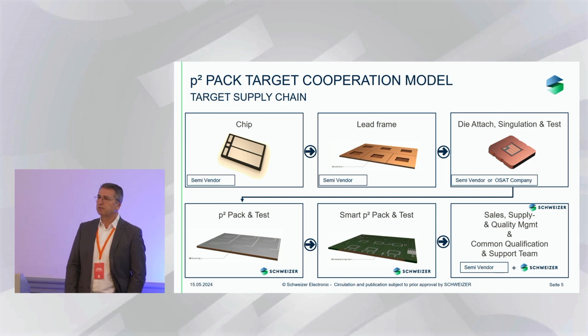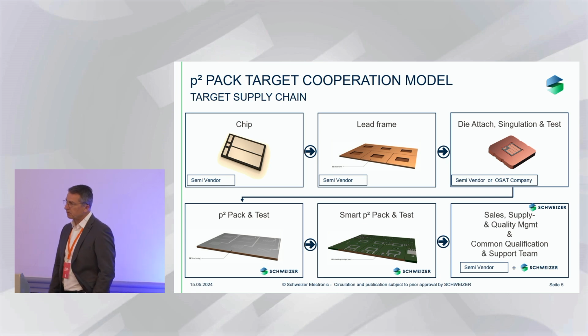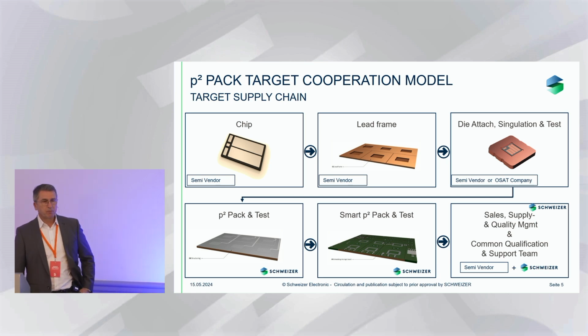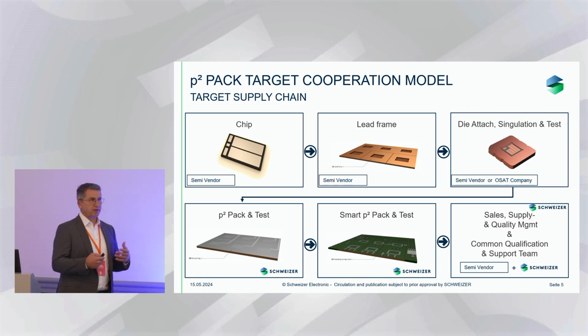The test is one of the most important points of this component because a fully functional test is very easy to perform or to carry out if you have a discrete device. On a bare die, you cannot have a fully functional test with a full current. And there are still some components failing after the first switching on, even though they are functionally tested on wafer level as good components. And this would lead to early failures in the embedding.